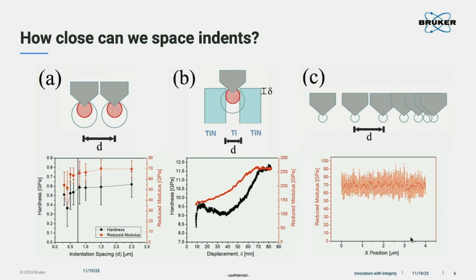And this is also about the contact depth, right? If we only make a very slight indent without any plastic deformation, that will be easy because there is no indentation mark. Then we can do very close indentation. Then we get a very high resolution image. This we call the modulus mapping. But you are not going to get the hardness value because you don't have any plastic deformation here.